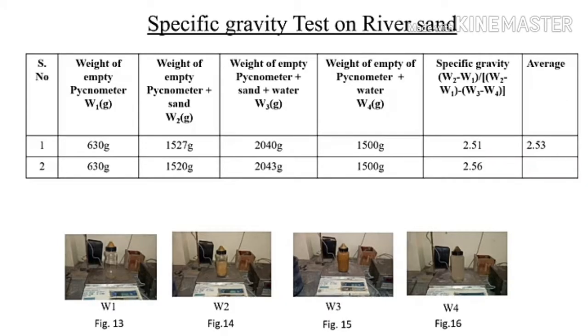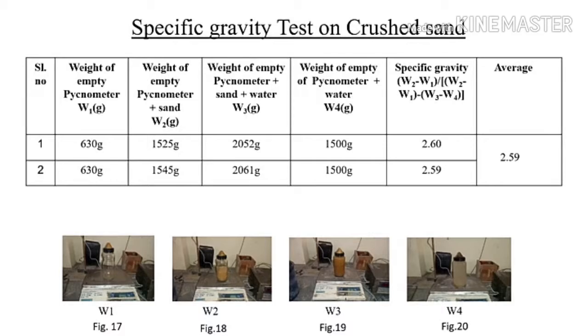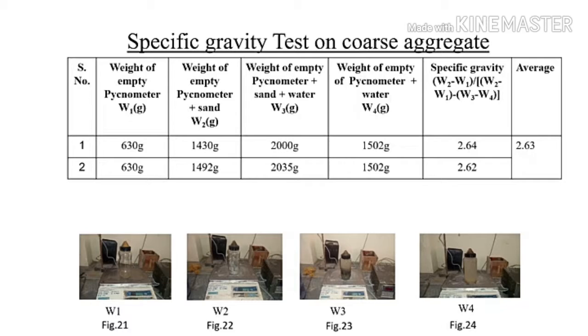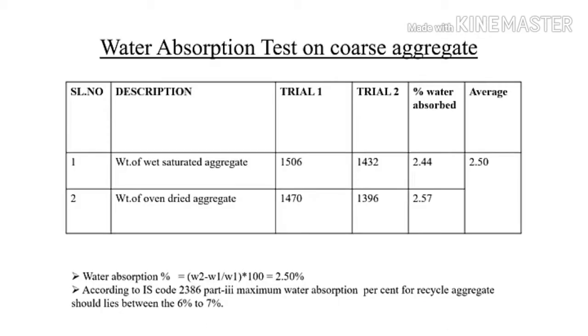Specific gravity test on river sand was found to be 2.53 as an average. Specific gravity test on crushed sand was found to be 2.59 with 2 trials. Specific gravity test on coarse aggregate was found to be 2.63 as an average. Water absorption test on coarse aggregate was found to be 2.50 as an average with 2 trials.